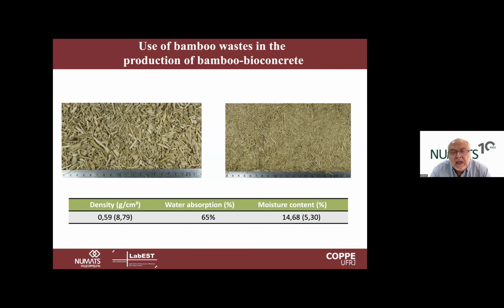So we have about 8 to 10 times aspect ratio. The length of this crushed comb is about 8 times more than the typical cross-section dimension. If we grind a lot, it's more circular, but otherwise it has like a 2D cross-section. And the density of this material is around 600 kilograms per cubic meter.